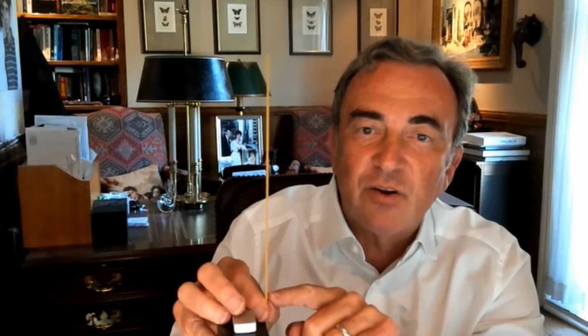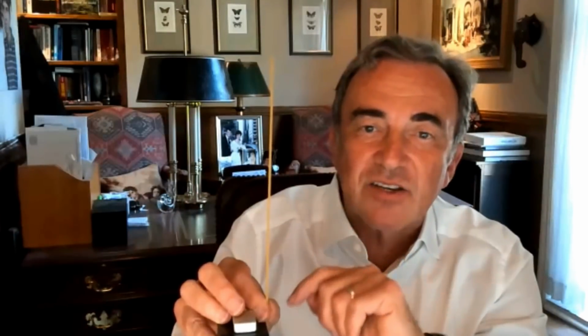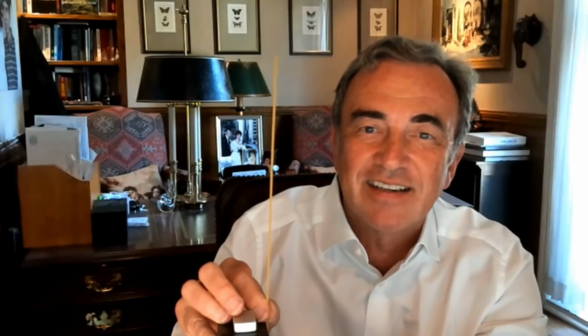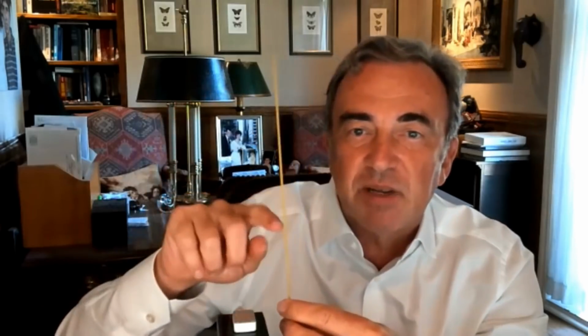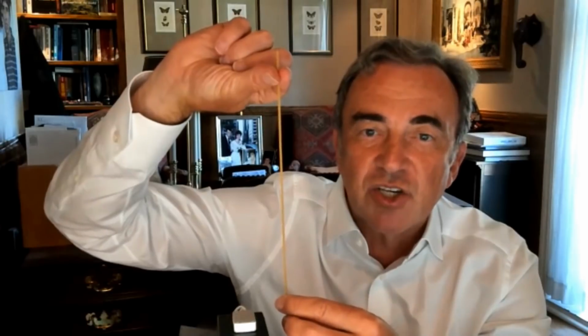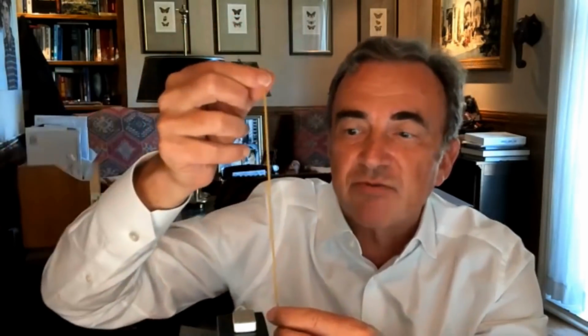And what happens is that the mobility of electrons in lithiated nanowires is excellent. It's actually faster than the mobility of electron in graphite. So the silicon becomes amorphous, and you have very fast charging speed because electrons move very quickly on the length of the nanowire during charging, and a lot of power because electrons move out very quickly during discharging. So you not only increase charging speed, you increase power density. Nice.